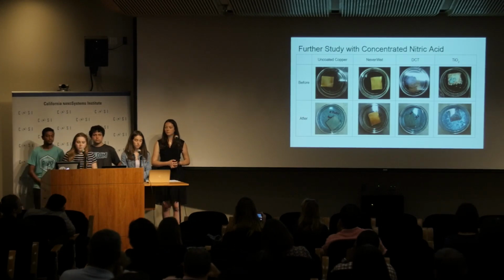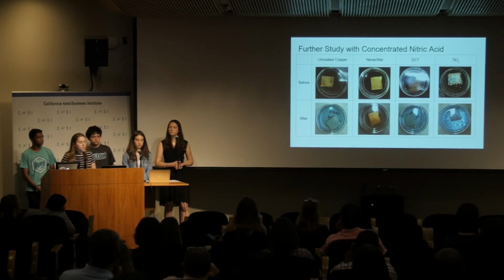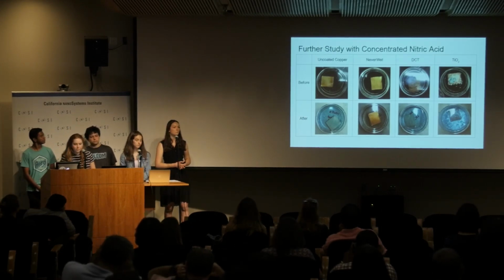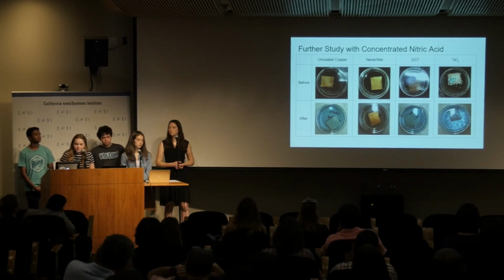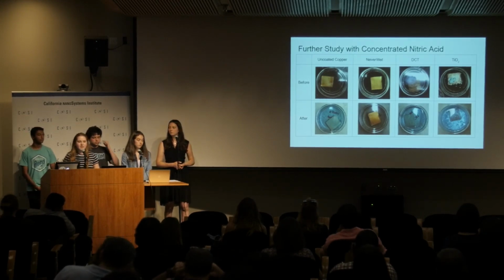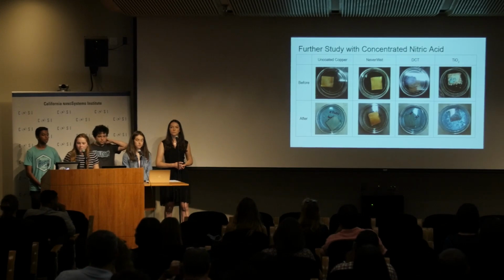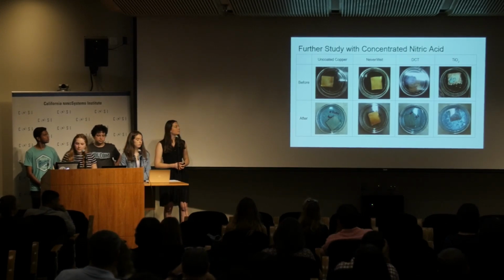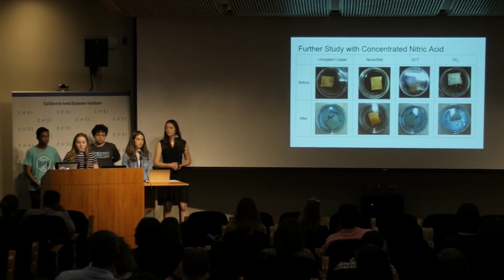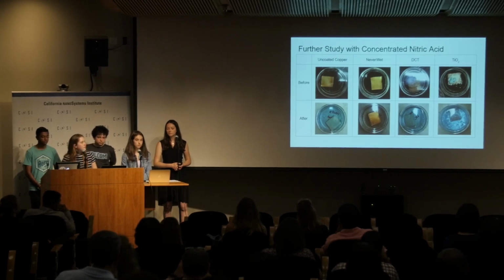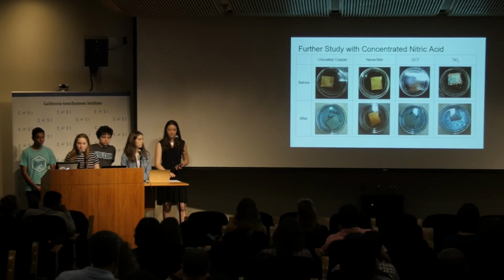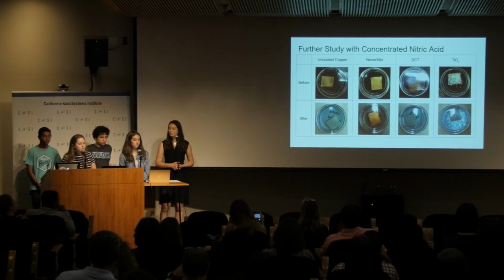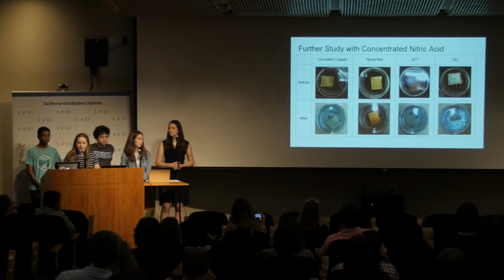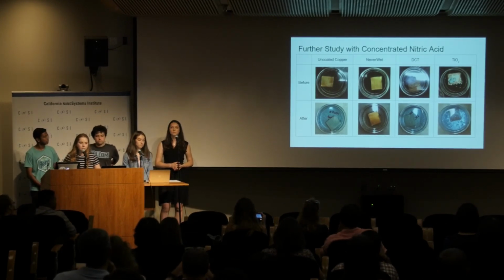Okay, so we conducted a further study with the nitric acid to represent long-term corrosion in the limited time frame that we had, which is 2 days. We can see that the nitric acid in fact reacted with the uncoated copper, DCT, and TiO2, except for the never wet. And the TiO2 and the DCT in fact became hydrophilic, but the never wet stayed hydrophobic.